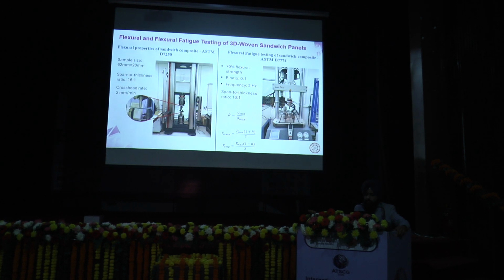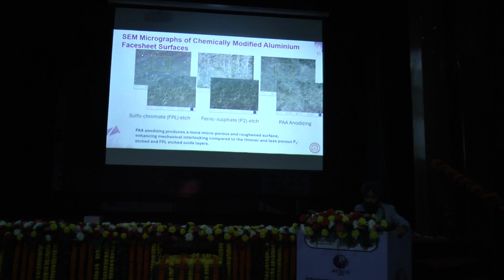We used ASTM D7250 to assess the flexural performance, and for flexural fatigue we used ASTM D7774. We took 70% of the flexural strength for fatigue. The R ratio is 0.1 and frequency is 2 Hz. The span to thickness ratio in both cases was 16:1.